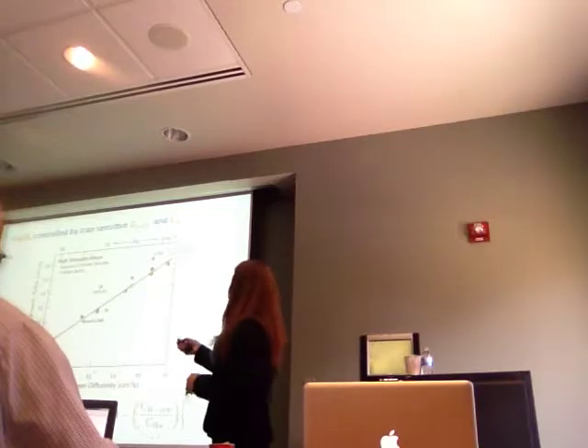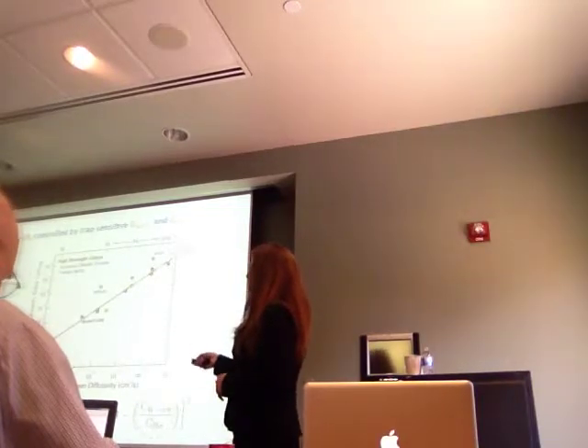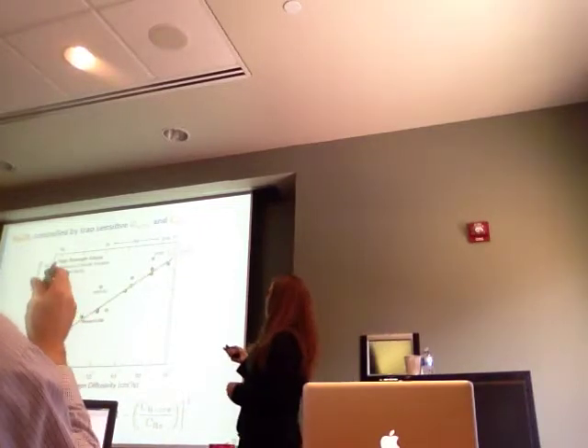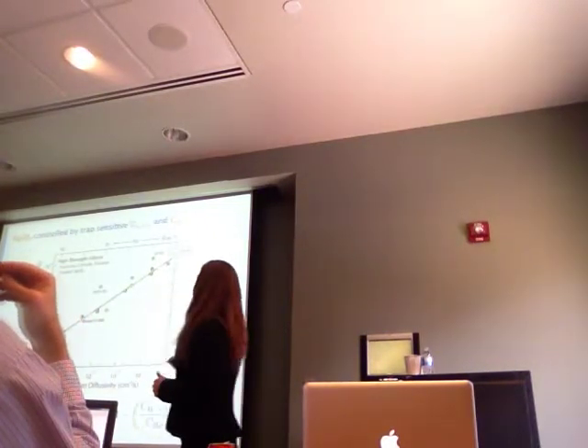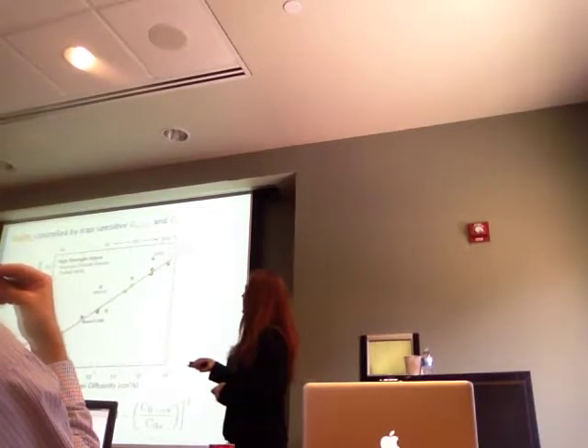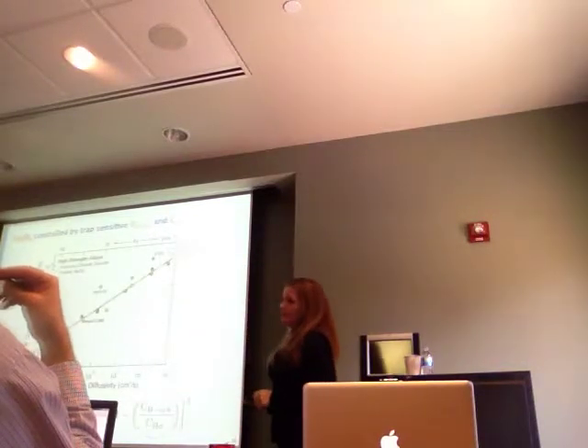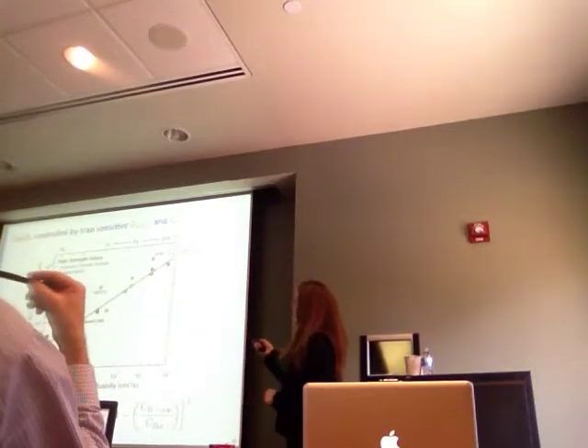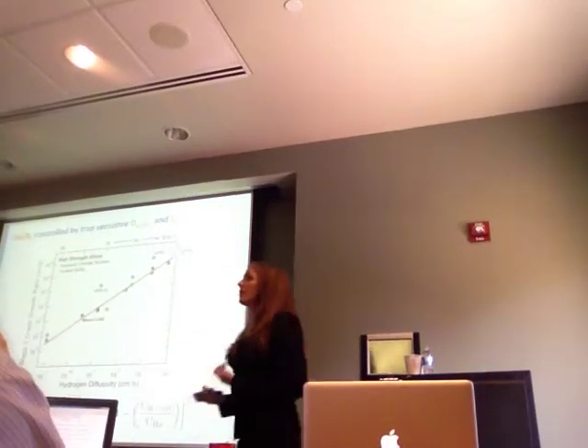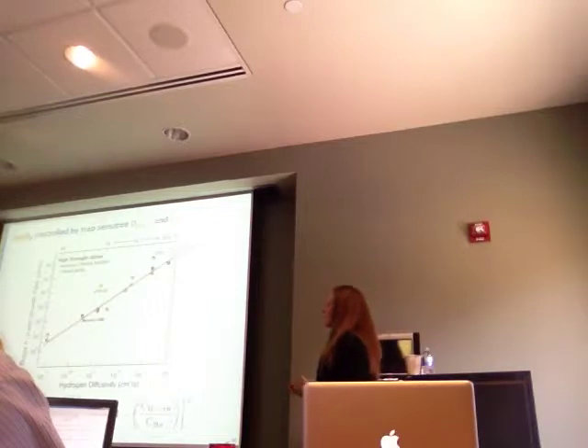So this plot was put together by Professor Gangloff. He took stage 2 crack growth rates of several high-strength alloys, nickel, aluminum, iron, titanium, all of them loaded in chloride solution, and he plotted these crack growth rates, the fastest measured, against their hydrogen diffusivity. And you can see that all of these crack growth rates correlate very well with their hydrogen diffusion rates. So that means that these rates are likely hydrogen diffusion limited.